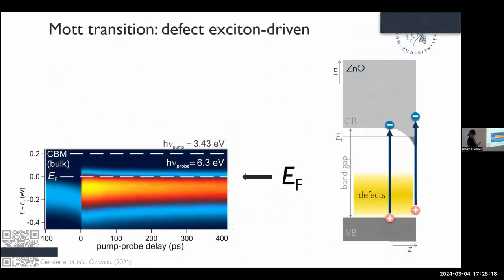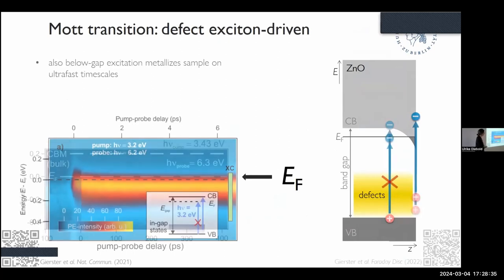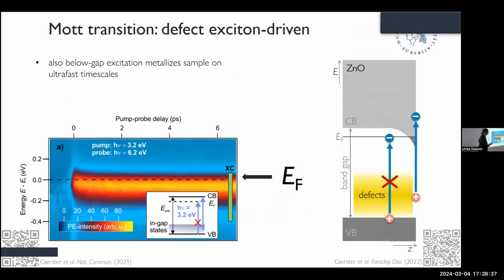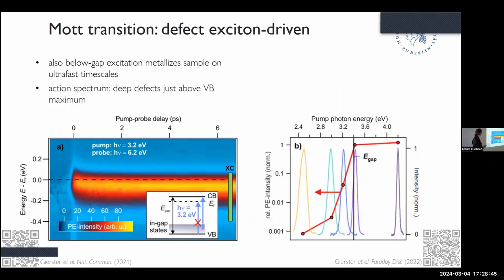We then wanted to make sure that it's really defect exciton and not something else. So in the experiment I showed you already, we used 3.4 eV, resonant with the band gap. And then we tuned the pump photon energy so that we cannot get across the band gap anymore. And you see that you can see the same behavior also for smaller photon energies. You can do this in a sort of action.